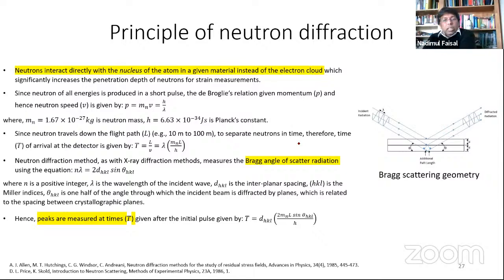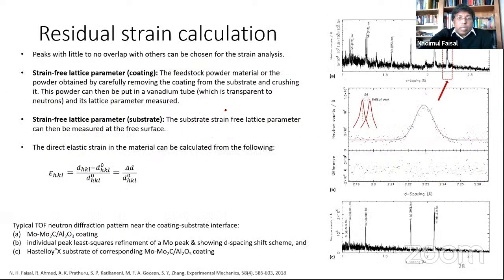So that's the advantage, that you can read the strain inside the volume, which is not possible using the X-ray method. You can use a synchrotron to an extent, but in my opinion, neutron can give you much better results. Well, that is expensive, but the methodology is very similar to what you do in X-ray. The fundamentals are the same. You can use this geometry or Bragg scattering geometry. And one thing you have to think about is that your peaks are measured in time. So what is the time? You can use these d_hkl, mass of neutron, length of the flight path, and theta_hkl, and h is the Planck's constant. These things can help you get started with the measurement plan.